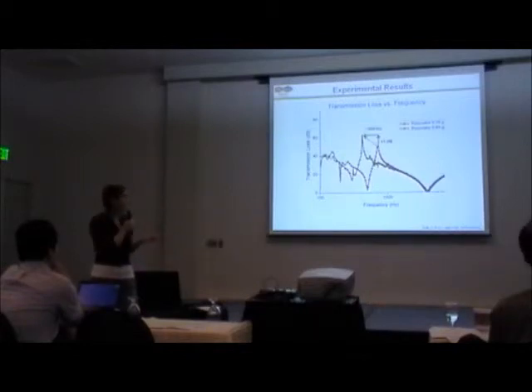the transmission loss peak increases in magnitude and decreases in its effective frequency. And we can get about a 300 Hz decrease in our frequency, which is what we want, this low frequency response.